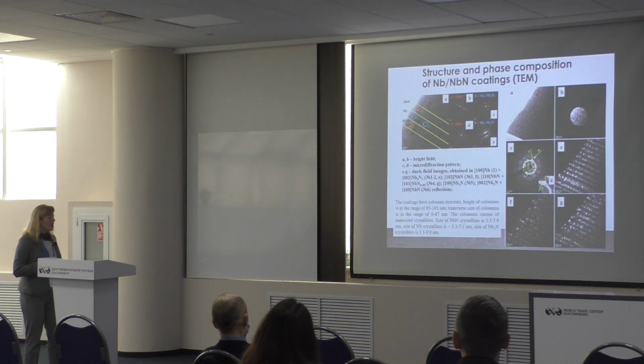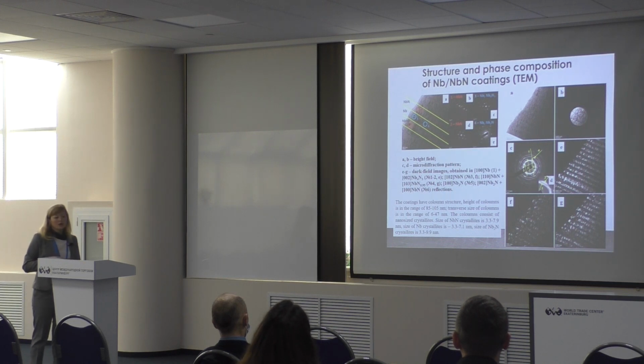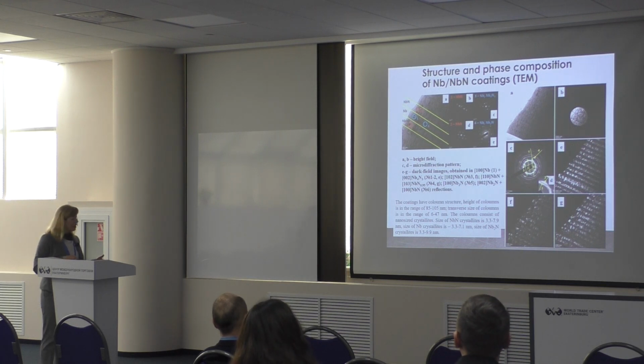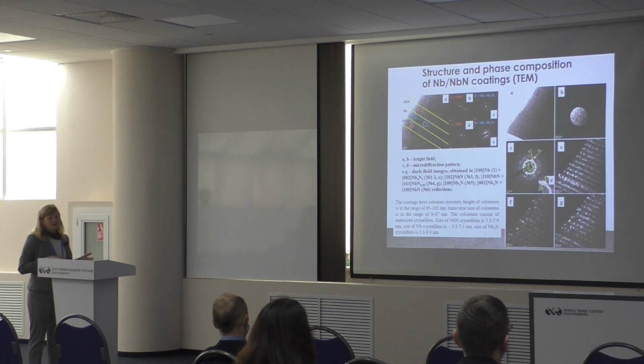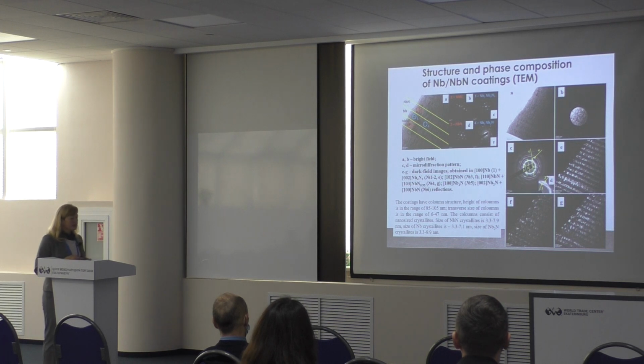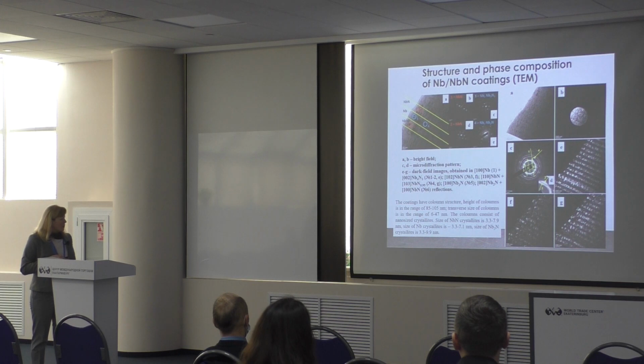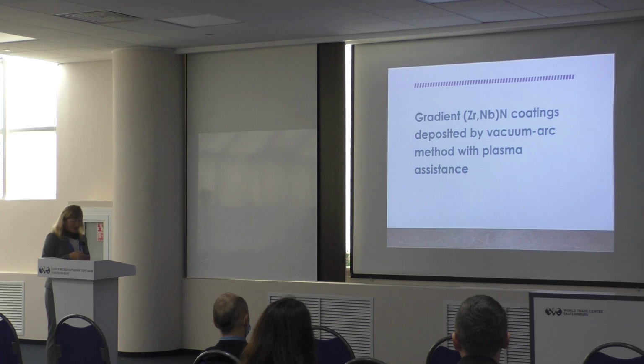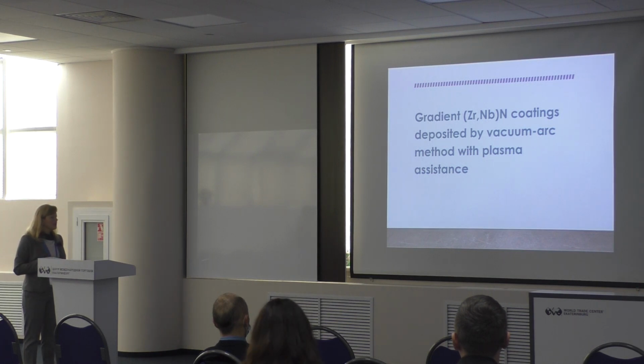To conclude this part, I want to note that this is only one example of multi-layered systems of metal nitride type, and we can deposit these multi-layered coatings by plasma-assisted vacuum arc deposition, but it is a problem to form a pure metal layer. The next system is gradient zirconium niobium nitride coatings deposited by vacuum arc method with plasma assistance.